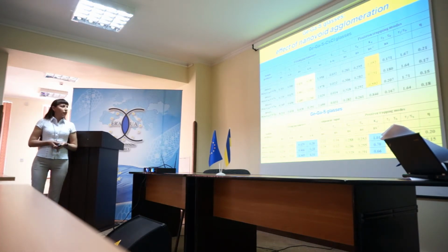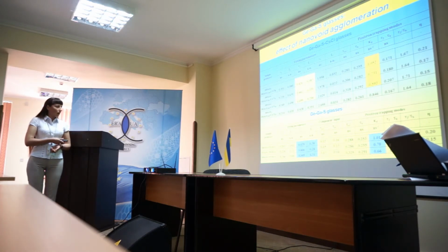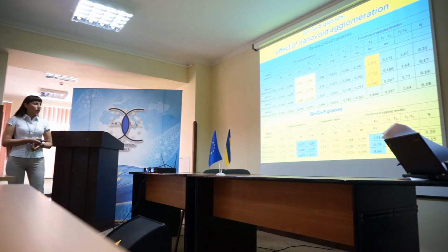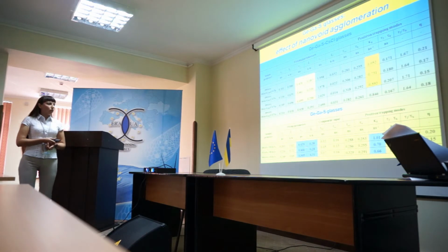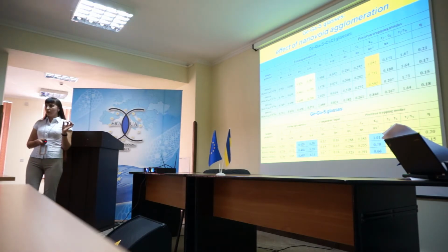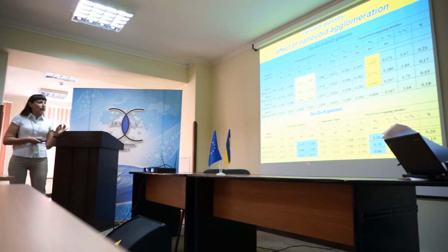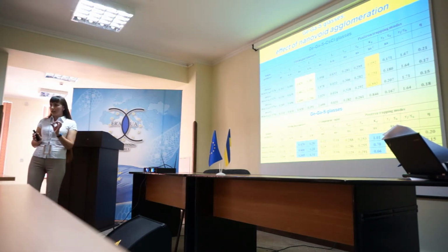So in the case of different base glass systems with different amounts of germanium and gallium, we have also an increase of lifetime of the second component and a decrease of intensity of this component. Lifetime of this component reflects the size of this free volume, and intensity reflects the quantity or concentration of defects in these materials.